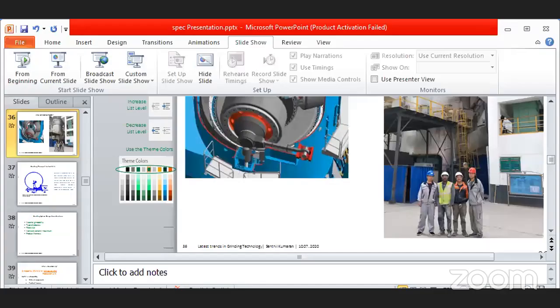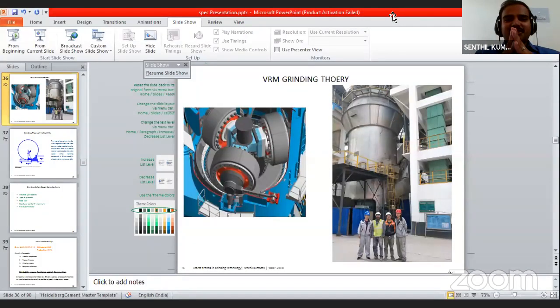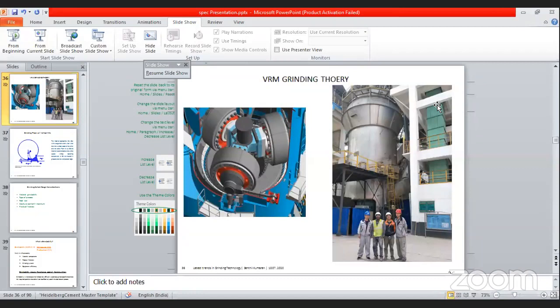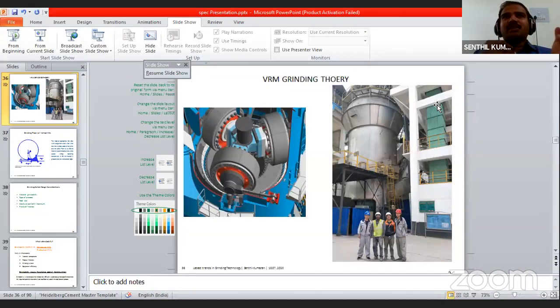Yes, Prem Kumar has asked how you will control heat loss in a ball mill. Heat losses, basically, when we put more media in the ball mill, more heat will be generated. We need to control the product temperature as well. So what we do is add water spray to the system. We have inlet as well as outlet water spray control. The water spray controls the temperature, and then the losses can be controlled by adding appropriate grinding media sizes. For example, in the first compartment we add 90 mm, 80 mm, 70 mm, 60 mm, like 4 or 5 sizes of grinding media. It depends on how much percentage you add to each. For example, we cannot add 100% 90 mm media.